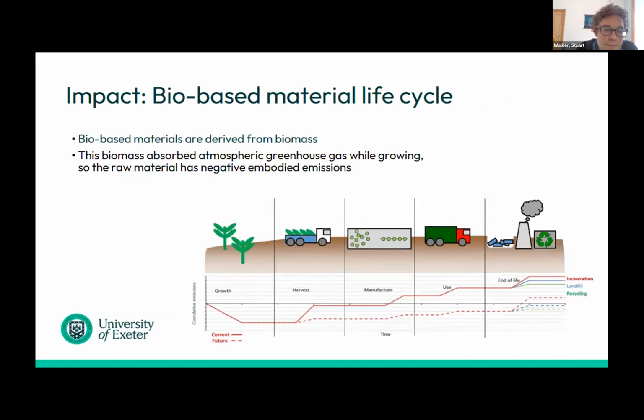So in a comparative bio-based case, you can see the horizontal axis is actually through the middle here. If you notice, it's moved up, and that's because during the growth phase, so the first stage of the bio-based material, when it's a plant growing, it's actually absorbing atmospheric CO2. So it's taking in greenhouse gas from the atmosphere, and that's stored in the plant. Then as we harvest it and again go through manufacture and use in various processes, we essentially use up that. So we don't use up that emission, but in net terms, we use that up.